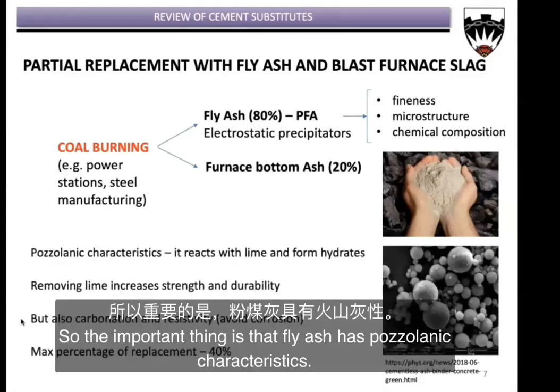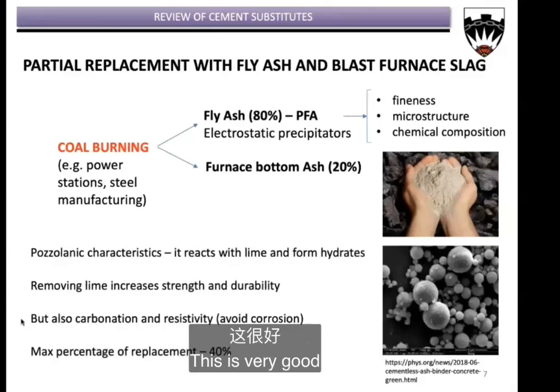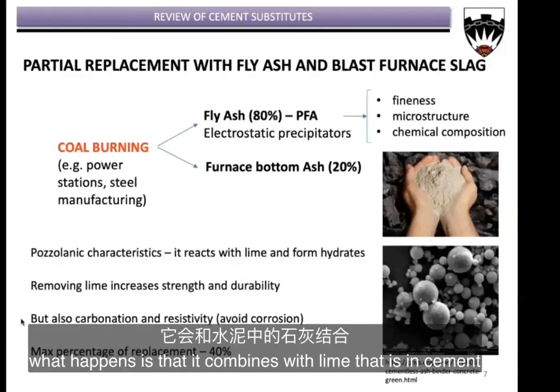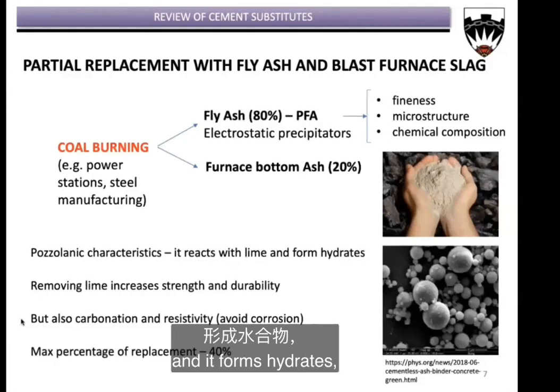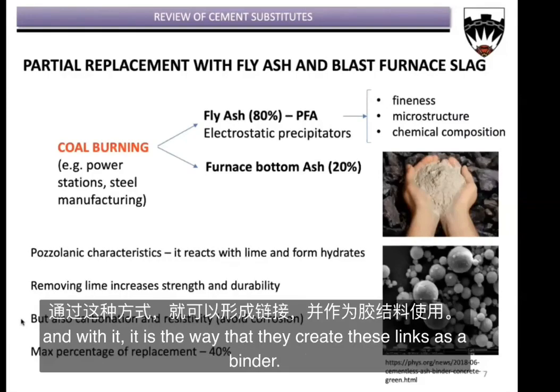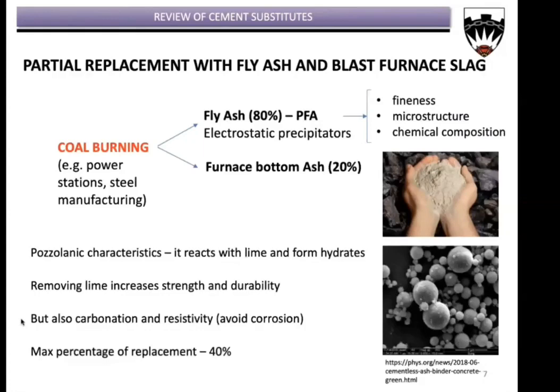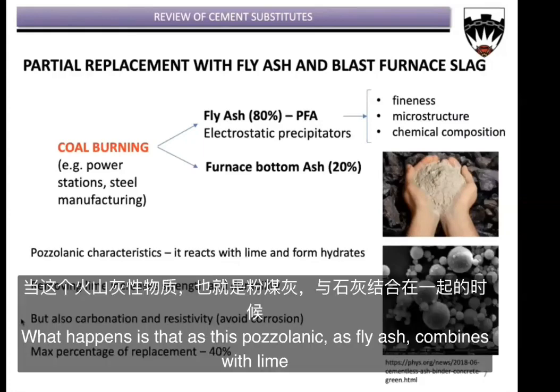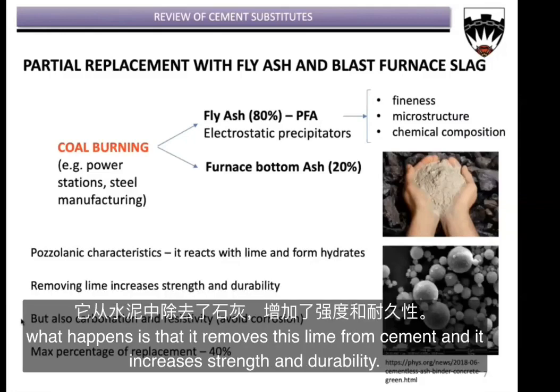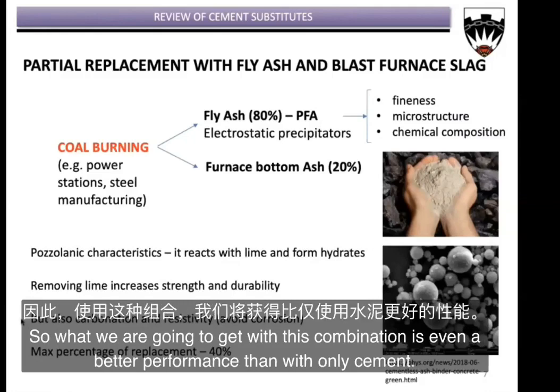So an important thing is that fly ash has pozzolanic characteristics. This is very good, right? So in that case, what happens is that it combines with the lime that is in cement, and it forms hydrates. And with it, they create these links as the binder. As this pozzolanic fly ash combines with lime, it removes this lime from cement, and it increases strength and durability. So what we are going to get with this combination is even better performance than with only cement.